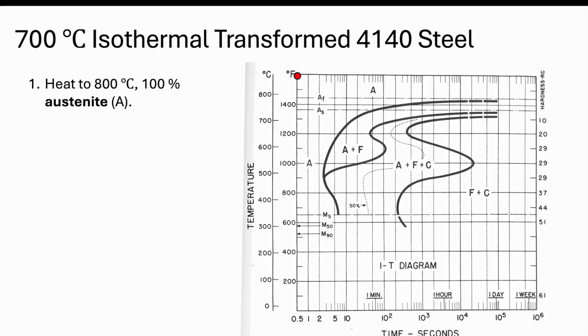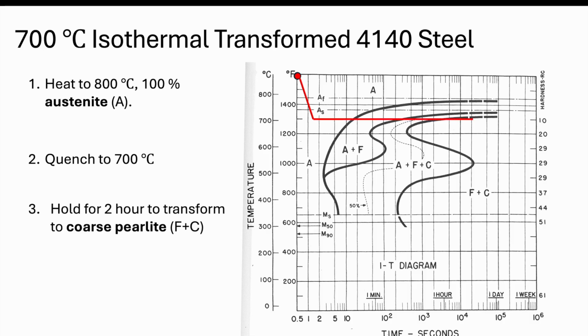All right, the last one we're going to do and talk about in this kind of experiment and progression through different microstructures is we're going to talk about 700. So same thing, start above 800, quench to 700 very quickly, and then hold. And in this case, we're going to need to hold for 2 hours or so. So here at 700, one thing you're going to notice is, again, we can kind of go through the same progression. So at this point here, within a matter of 10 seconds or so, it's going to reach this region.